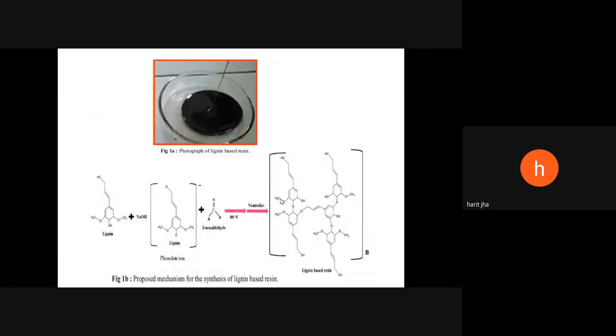In fact, we have tried to do that also in our lab and in experiments. We have tried to use this experiment in our MSc courses, wherein we have used the lignin as a material for synthesis of resin and polymeric material as well as for synthesis of adhesive. And these adhesives are then used for sticking of the tiles, wall tiles, as well as for wood material. So we have been successful in achieving the proper binding of wood material as well as the tiles, floor tiles as well as the wall tiles, using these resin materials.